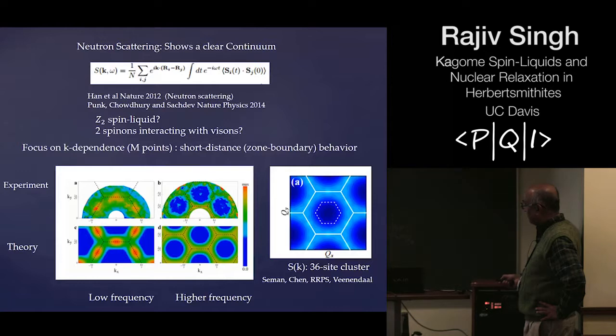So of course the most prominent feature is the absence of scattering near the center of the Brillouin zone, and the scattering is mostly along the zone boundary. Furthermore, at high energy this scattering is almost featureless, just the same as seen in experiments, but at lower energy it tends to concentrate a bit more on these so-called M points. Okay, that is kind of what is seen in the experiments over here, and actually this theory is somewhat phenomenological, but even if you just do an exact diagonalization, you see qualitatively these features already reflected in the properties of the system on a small cluster. So this is certainly some evidence that the system is forming a quantum spin liquid.